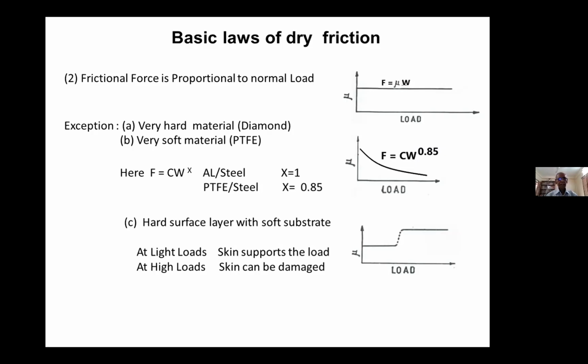For very hard material like diamond and very soft material like PTFE, this may not be true. Experiment shows that we can write F is equal to C W to the power x, rather than mu W. So if x is 1, it reduces to F is equal to mu W, and then the constant is the coefficient of friction. But if x is not 1, then we cannot call it coefficient of friction. We call it some constant, frictional constant, say C here. So F is equal to C W to the power x.